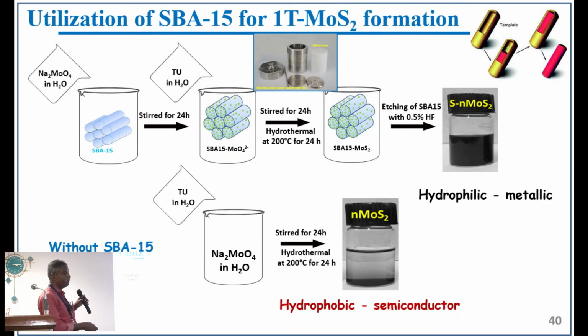So now we are going for the preparation of 1T MoS2 inside the SBA-15, where we took two types of precursors. The first one is sodium molybdate, because we want to establish a method based on the precursor also. So we used sodium molybdate dissolved with SBA-15, then used thiourea and stirred for 24 hours. Now the SBA-15 traps the Mo inside, and after that we went for hydrothermal treatment at 200 degrees for 24 hours, and then MoS2 is formed inside the SBA-15. After that we used 0.5 molar percent HF for etching the silica. So now we are removing the silica by etching it. That's the process we are employing here.